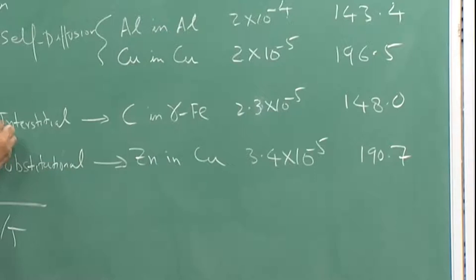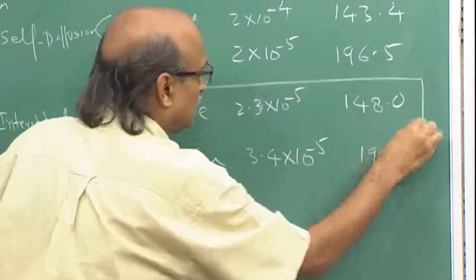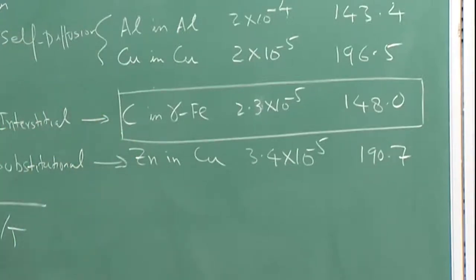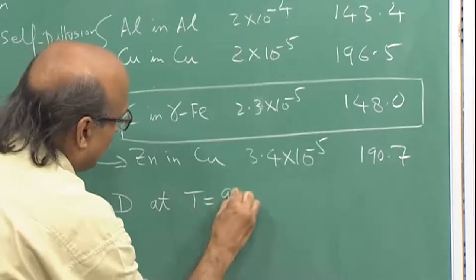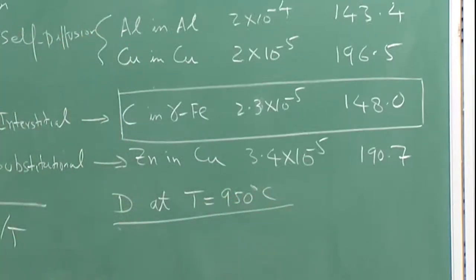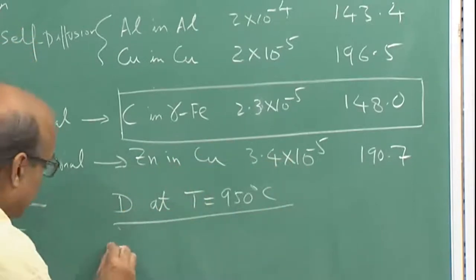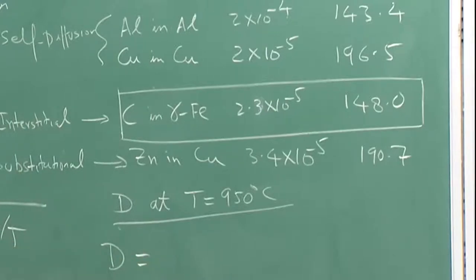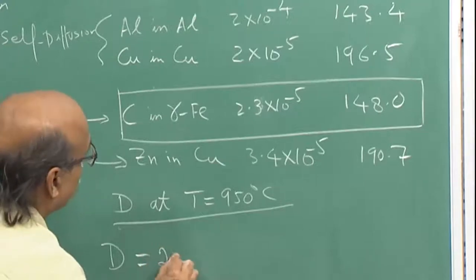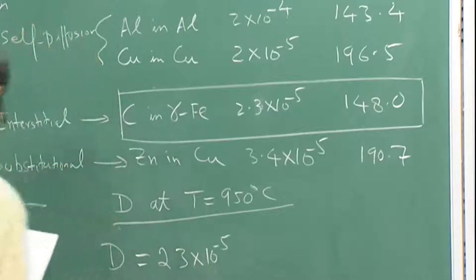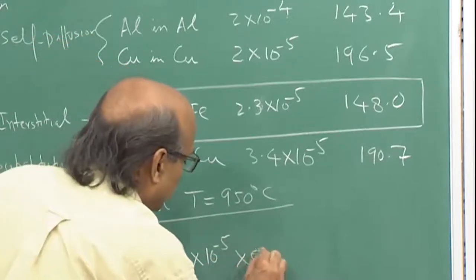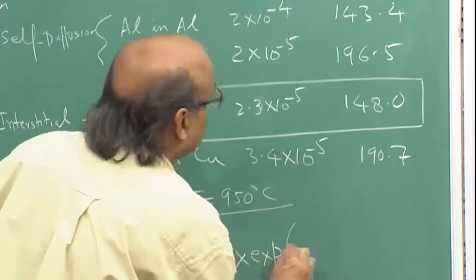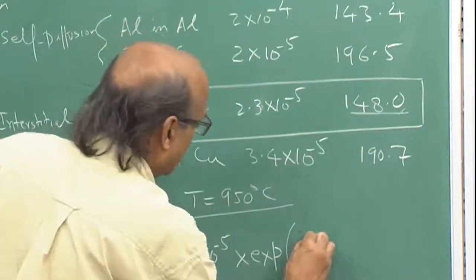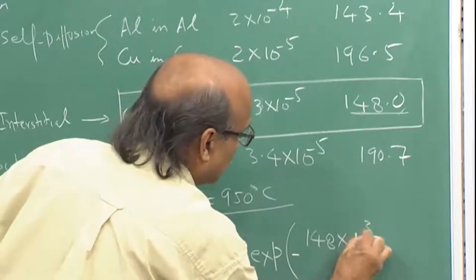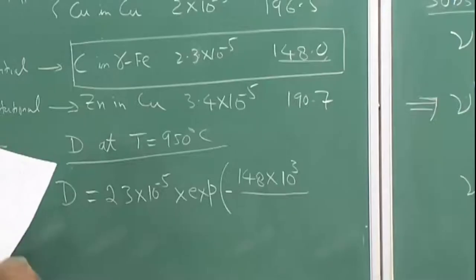If you take just one case, let us consider this case and find out what D, the diffusion coefficient, is at T equal to 950 degrees centigrade. Well, D is equal to D0 e to the power minus Q by RT. So, D0 is 2.3 into 10 to the power minus 5 times exponential minus 148, which is the value of Q, but it is in kilojoules. So, I have to multiply it by 1000 to convert to joules,